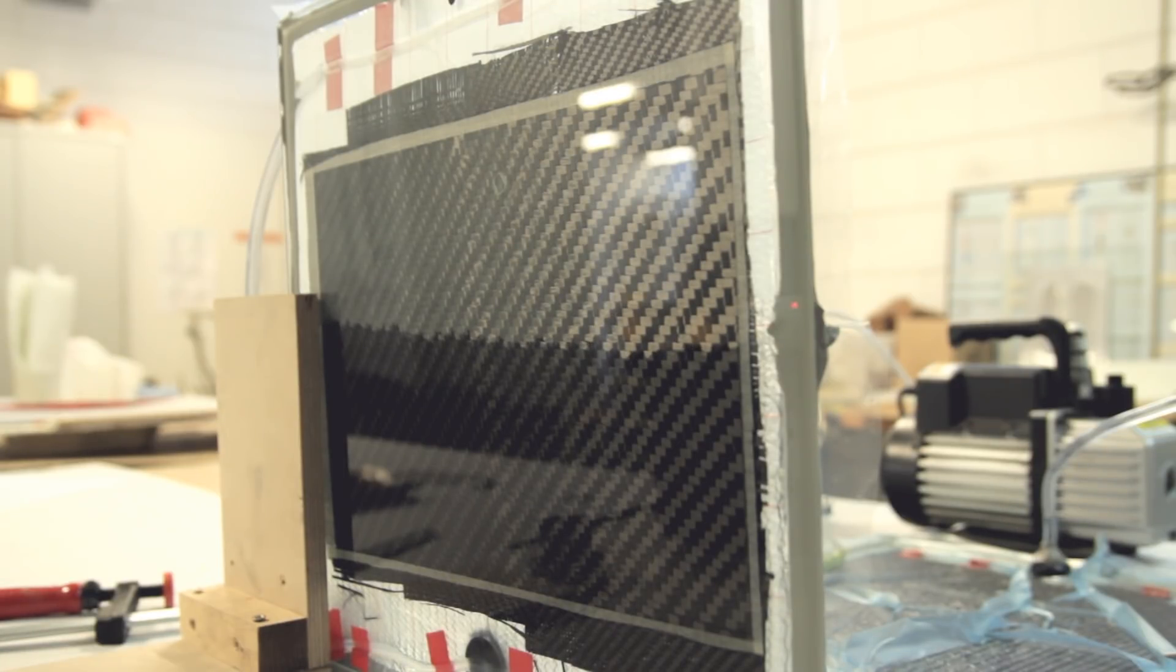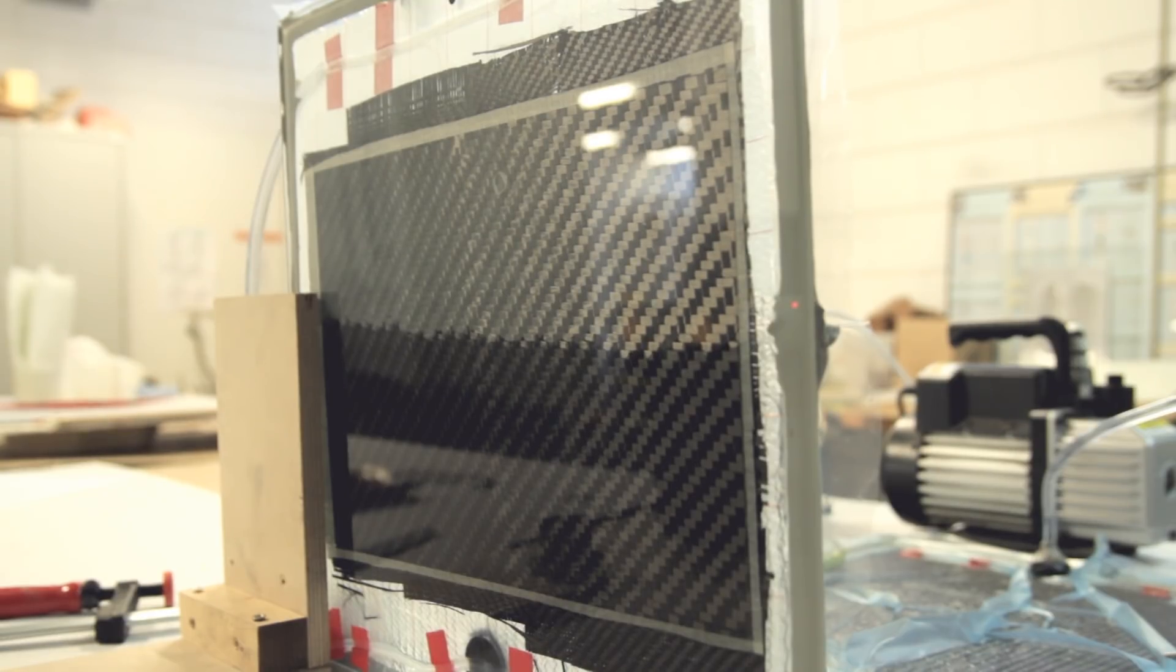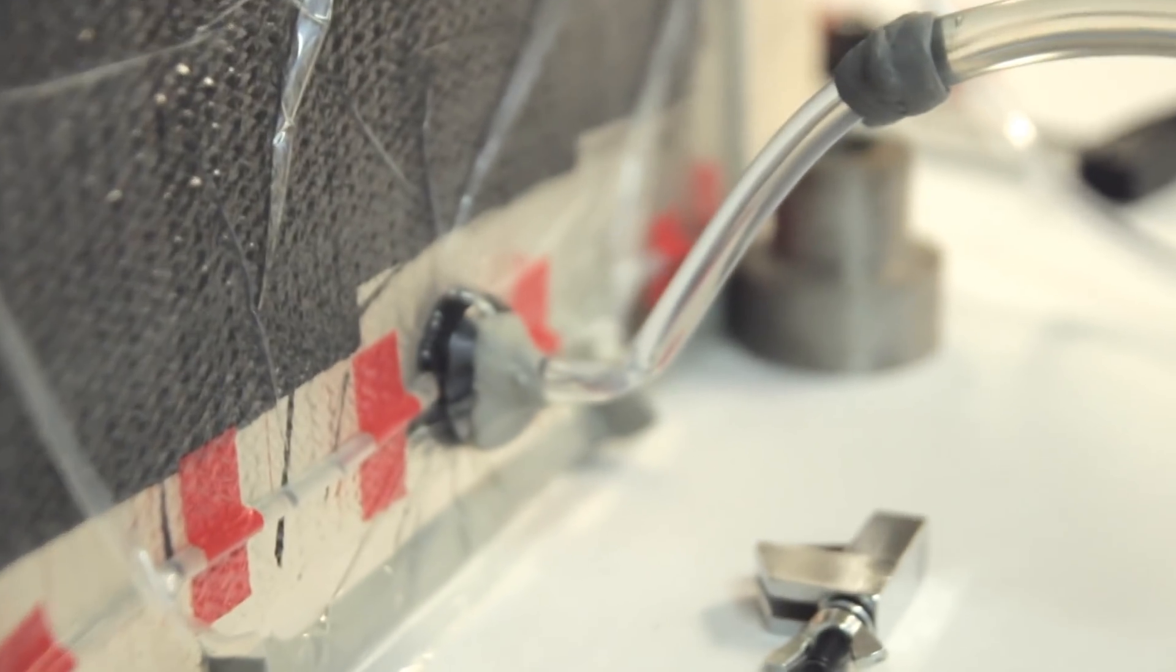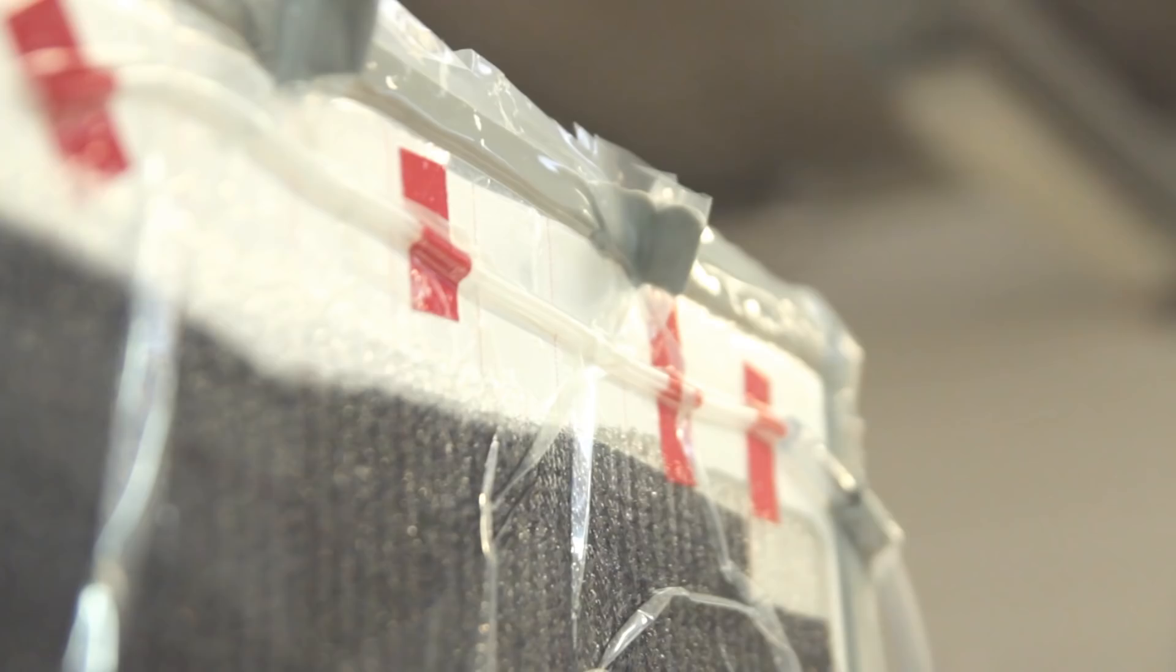Something you need to know - vacuum is not something you have against gravity, so gravity doesn't matter, it's just the vacuum. I really think this is a cool shot because here you can see how the infusion is done. It's not like you have a full front on the other side thinking everything is saturated on the back. You can see it saturates slowly and not evenly, so this is something very interesting you can learn.